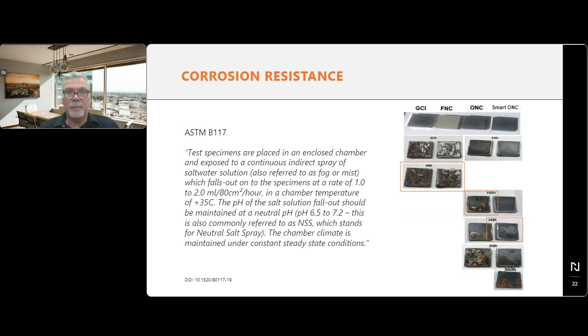It is still a baseline, and this baseline is critical because it allows us to see if the improved post-oxidation called the Smart ONC works better than regular FNC or regular FNC plus regular post-oxidation. And this is of interest because we can provide ourselves with some feedback. So what you see on top here is just gray cast iron, Ferritic-Nitrocarburizing, ONC, which is post-oxidation, Smart ONC, which is the improved post-oxidation that seals those defects in the white layer, among other things.